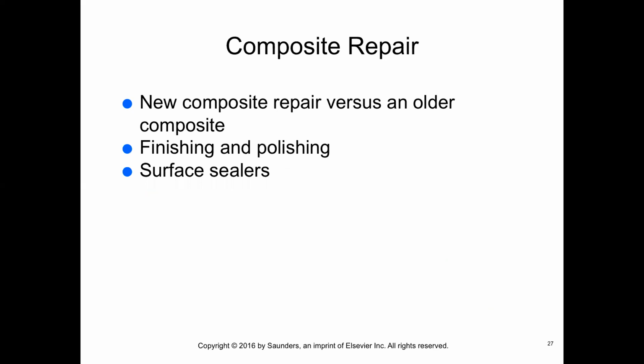It's been estimated that about 60% of all operative dentistry done is to replace failing restorations. Two common reasons for failure are fracture of the restoration and recurrent caries. Small fractures in a composite can be repaired rather than replacing the entire composite restoration. A repair of a new composite is optimum because the two materials will have a chemical union. In an older composite, there will be fewer unreacted methacrylate groups present, and the bond will be weak.